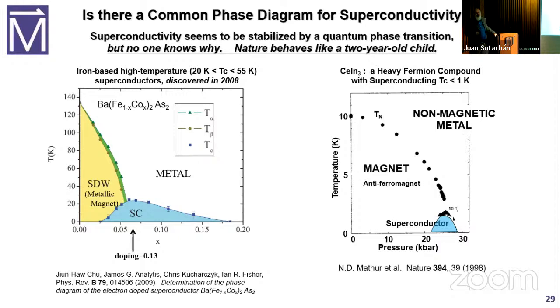We have no idea why, but this is the only rational strategy for looking for superconductivity. Find a magnetic phase that's dropping to 0 temperature as you vary a thermodynamic parameter, number of electrons or pressure, and when you get to the point where it should be going to 0, more often than not, you see superconductivity. In fact, now, when we don't see superconductivity, we think maybe the sample is too disordered and we need a higher quality sample. We've switched our thinking from what the heck is this doing here to why are we not seeing superconductivity? We have no idea why there might be this common phase diagram for superconductivity.